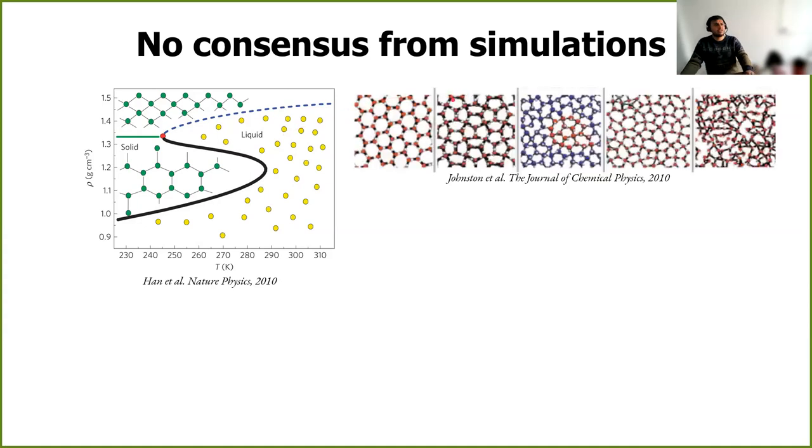However, if you look at another force field, for example, this is the MW model. It has a three-body component to the model, while this only has pairwise interactions between water molecules. And there they started observing more interesting phases. This is, for example, a pentagonal phase of water. And then they find something where you have some twisted pentagons and hexagons, and of course some disordered phases as well. So changing the force field again takes you from a simple phase diagram to something much more complicated.